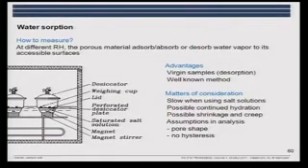So how do you do it? And that was the question we had earlier. Here we have the old-fashioned way, where we have desiccators with our samples, and down here we have a salt solution. And typically you will keep it in a box which is temperature controlled, and you will have stirring, so you ensure that you have the right water vapor pressure above.